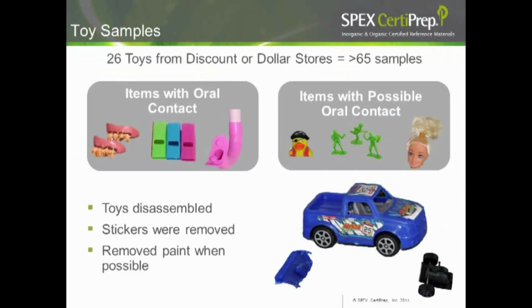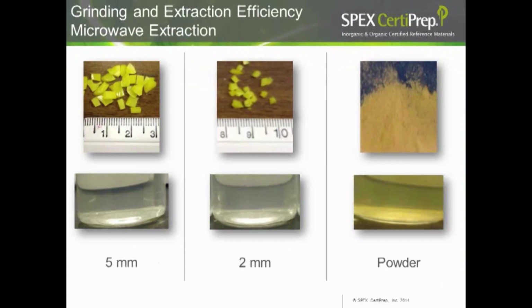Now, we had used these toys in a previous study that we referenced a year or so ago, where we did organic components on these toys. For that study, we were following a CPSC method, which suggested the toys be cut into under 5mm pieces. We were not sure if the actual size of the particles was going to greatly affect our extraction at that time. So we did a little study and we extracted 5mm pieces, 2mm pieces, and some powder. You can see we got a lot more extract from that powder than we did from the larger chunk pieces. When it comes to sample digestion, a fine powder is a little easier to digest, or at least uniformly digest, than a large 5mm or 2mm piece.